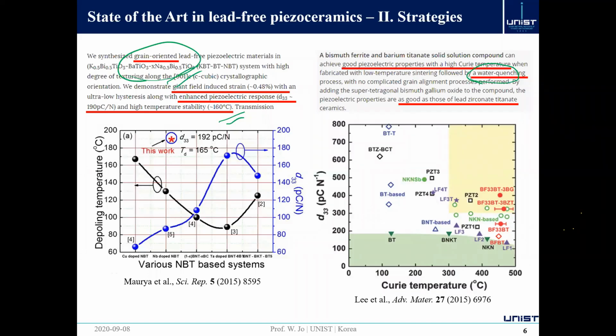So what these people did was quench the sample quickly from the temperature where this metastable phase doesn't exist, bringing it down to room temperature so that they can get phase pure bulk lead-free materials. But as you can imagine, the problem would be thermal shock.